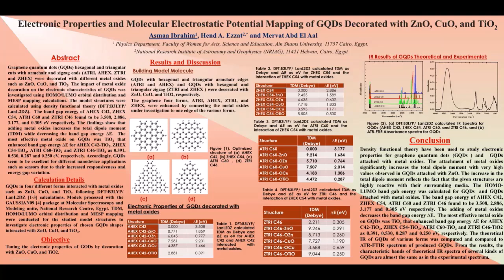The theoretical IR of graphene quantum dots of various forms was computed and compared to the FTIR spectrum of produced graphene quantum dots. From the result, the characteristic bands of theoretical IR spectra of several kinds of quantum dots are almost the same as in the experimental spectra.